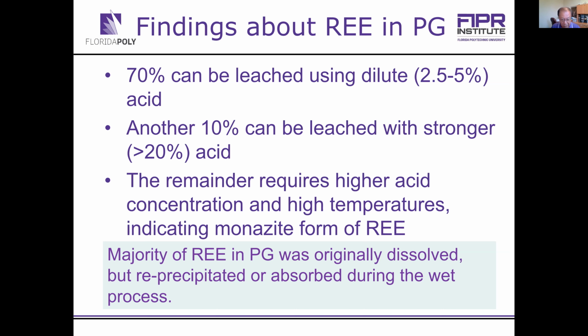They are not undissolved rare earth compounds, because when we ran the leaching test on the phosphogypsum using dilute sulfuric acid, we could recover much of the rare earth elements, up to 80%, from the phosphogypsum. That's the indication that those rare earth elements were initially dissolved. They just probably got reprecipitated or absorbed on the phosphogypsum surface. So it's easy to leach. If they existed in rare earth minerals, you could not leach them with dilute sulfuric acid.